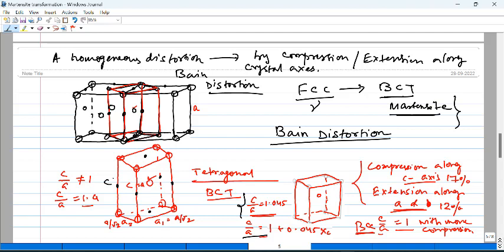So therefore, when you increase the carbon content, the chances of voids being filled along the C axis will also increase. And if you have presence of carbon along the C axis, compressing it along that axis will be difficult, right. And therefore, as you increase the carbon content, the C would increase, as you could see from this particular equation, right.